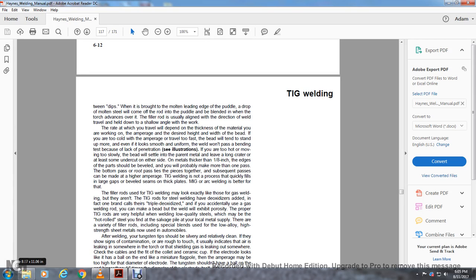If you are too cold, the amperage too low, or you travel too fast, the bead will tend to stand up more, even if it looks smooth and uniform. The weld wouldn't pass the bend test because of the lack of penetration. See illustration. If you are too hot, moving too slowly, the bead will settle within the parent metal,